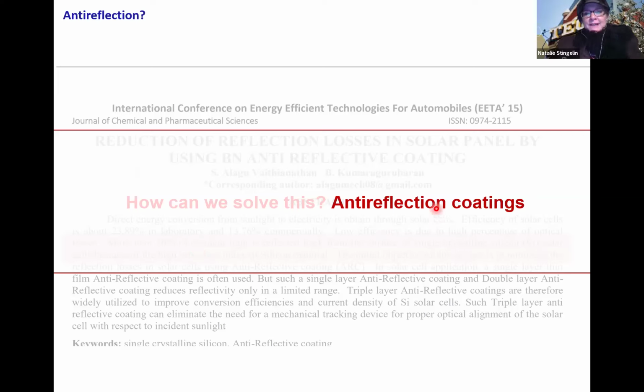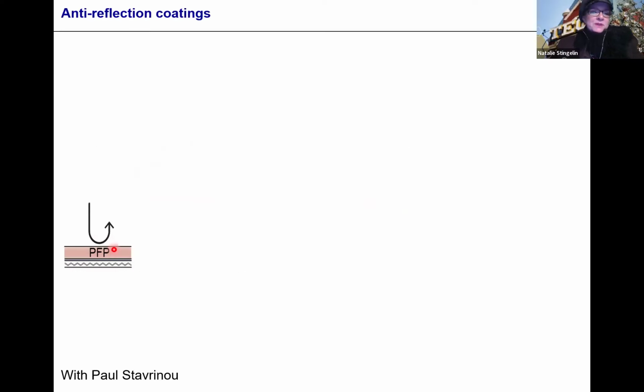The most simple one is really anti-reflection coatings, and this has been done. In many cases, they simply use fluorinated polymers, like PFP. Why fluorinated polymers? Because of the fluorine, they have relatively low refractive index. So if you come from air, low refractive index, to fluorinated polymer, bit higher refractive index, there's a gradual change to